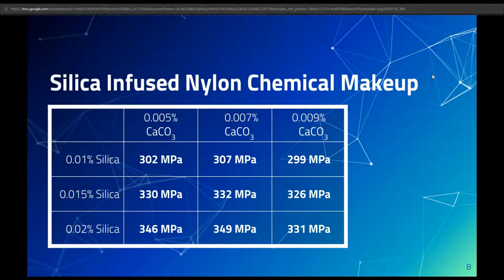This table shows the different combinations of silica and calcium carbonate with the nylon 6 polymer. The maximum tensile was achieved at 0.02% silica and 0.007% calcium carbonate.